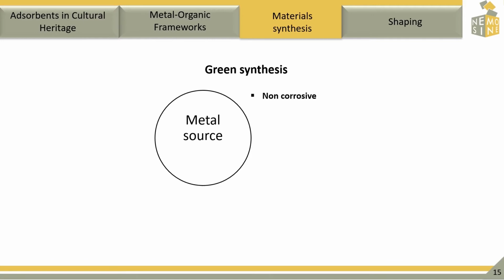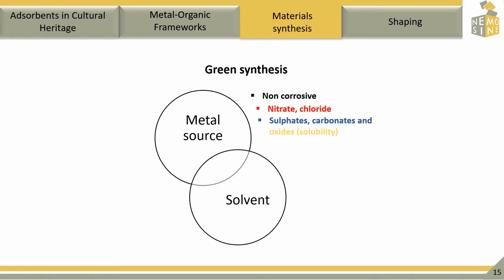So, in order to have a possible scale-up synthesis, we need to consider the most favorable synthetic conditions. This means, for example, considering the use of green conditions throughout the process. Thus, on one side, the metal source used should be carefully thought out to avoid corrosion, that not only increases the risks in the facility, but also increases the capital fixed investment due to the higher price of the building materials. This is what happens when choosing, for example, nitrates or chlorides as counterions of the metal source. While if we choose sulfates, carbonates or oxides, we will not have this problem, but they are more difficult to solubilize.